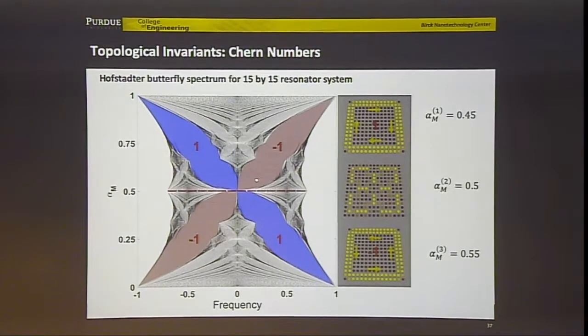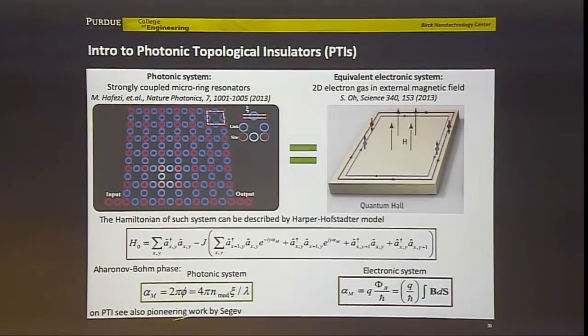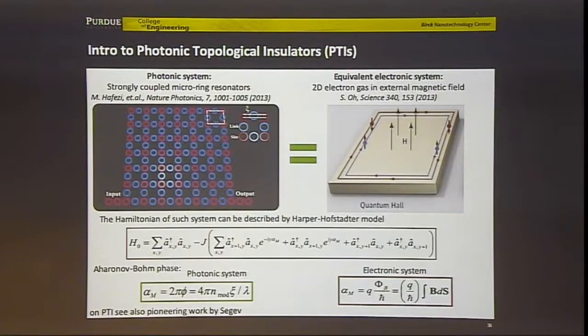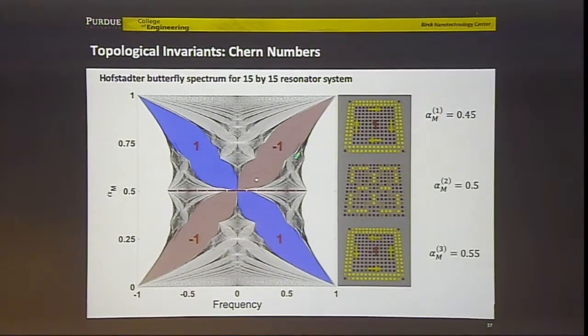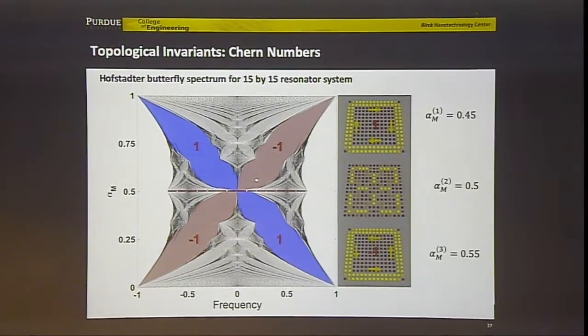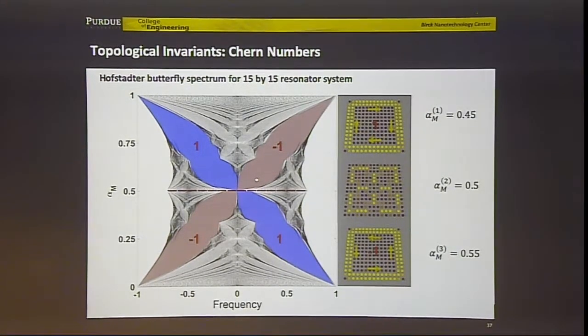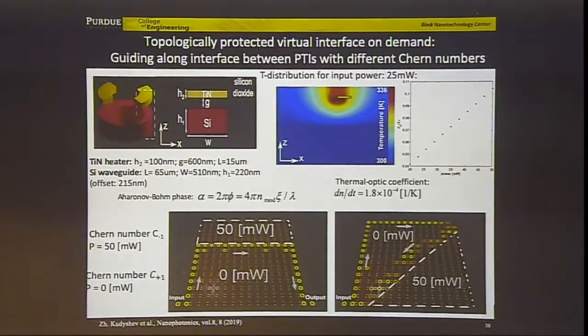And I can do it optically by changing the refractive index. If I change the refractive index so that I change my synthetic magnetic field, actually going from up to down, because that plays the role of the magnetic field, which is reflected in the fact that the Chern number becomes from negative to positive, I completely control my topological invariant. This is, again, the idea of the same guy, Vladimir Shalaev. I should give him all the credit. And to my knowledge, nobody suggested anything like this so far.